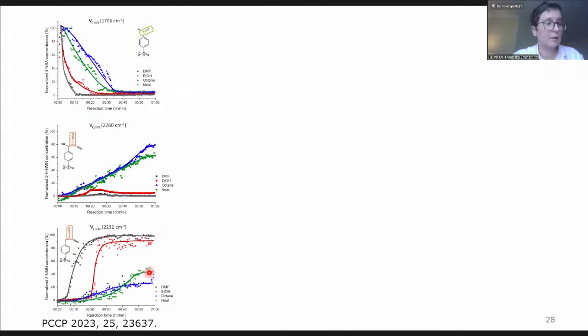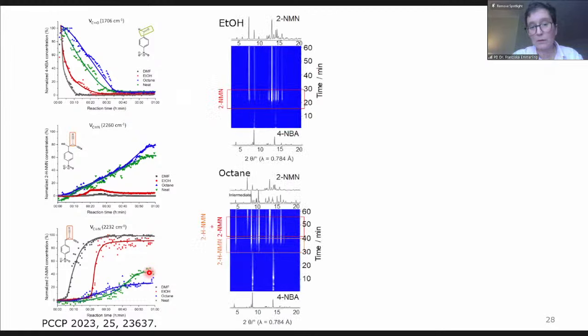So it takes longer for the conversion because we have this intermediate formation in the first place. So we also monitored that process with X-ray diffraction. Here you see the same picture. That's a direct conversion in case of ethanol. And here, when we use octane, we have the concomitant formation of the intermediate and the final product.